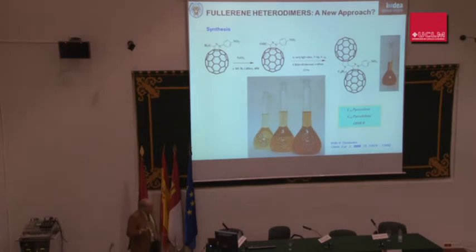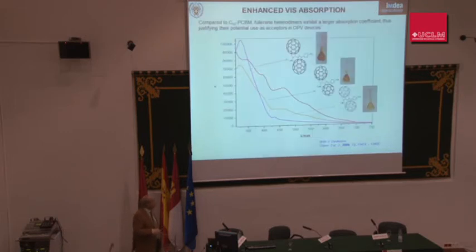Okay, so another step further in the synthesis of this material was these molecules, which were prepared in our group, with Juan Luis Delgado also engaged, and also Carmen Atienza: the synthesis of these dimers. Of course, this is C70, because you can see here that we prepared homo and hetero dimers, and this is C60, and the absorbance for the C70 is significantly higher. This can be observed much better here, in which the absorbance of this dimer having two C70 units resulted to be significantly higher than that found for the C60.